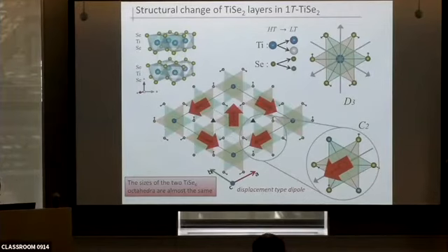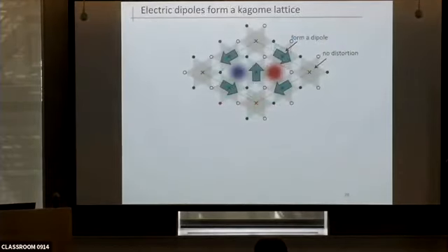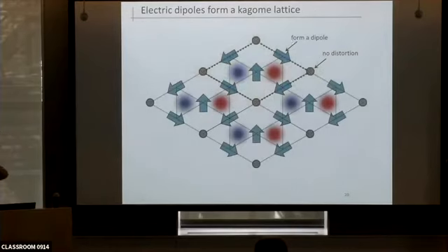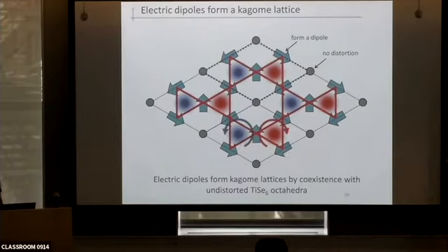Each dipole type octahedron is connected by a 2-fold axis. This is the excitonic phase structure, extending the drawing area. The appearance of two titanium octahedrons causes a kagome lattice of electric dipoles surrounding the no-dipole octahedron.